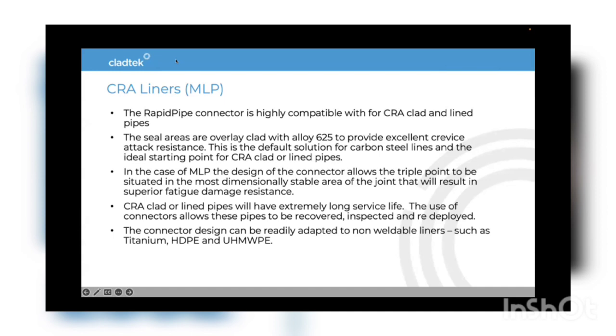Some of the specific benefits that we can get from using this connector is that the triple point, which is the area of great concern typically with a lined pipe, where all the interest in fatigue properties is focused. One of the benefits of the connector is we can have that triple point located well up inside the connector where it's thicker and more stable. So we think that using this connector, not only will the connector itself have a very high fatigue rating, but it will enhance the fatigue rating of the MLP as well. So we think it's a very useful technology in that regard.